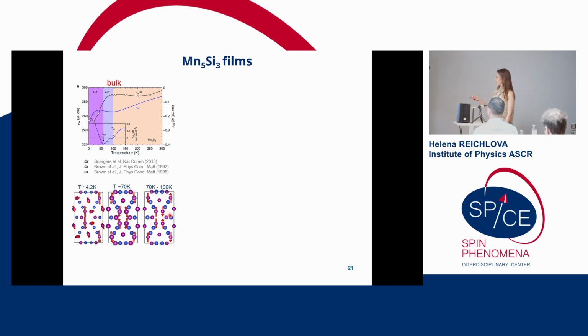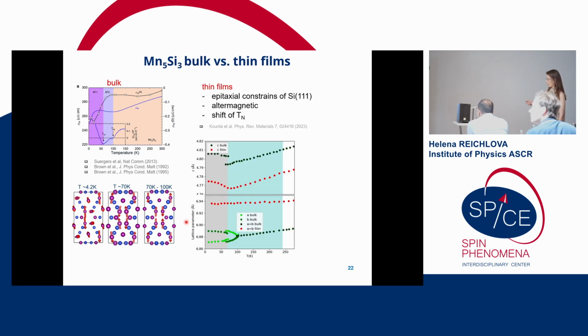It's a little bit more complicated here because in the bulk this compound is known to undergo several structural transitions, which are accompanied by a magnetic phase transition from the high temperature collinear phase at room temperature to some non-collinear phase at lower temperature. However, when this material is grown by MBE on a silicon substrate, the epitaxial constraints actually stabilize this hexagonal unit cell, which in the bulk is allowed only in the room temperature phase. And the stabilization of the hexagonal phase we also confirm by temperature-dependent structural studies.